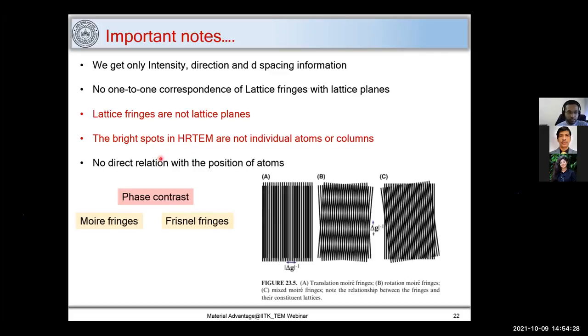There is another contrast which comes from Moire fringes and Fresnel fringes. That is also a phase contrast because of the change in the phase. And that happens when there is a slight shift in the atomic planes. So there is a translation of one atomic plane over another atomic plane, and you see this kind of fringes. If it is rotated, you will get this kind of fringes, and this is a mix. So it is translated as well as rotated. So whenever you see fringes in a TEM micrograph, those are because of phase contrast.